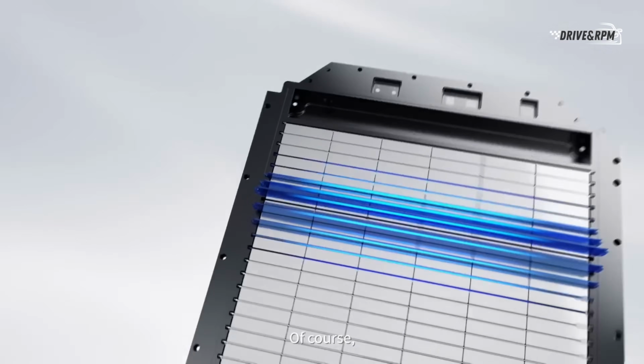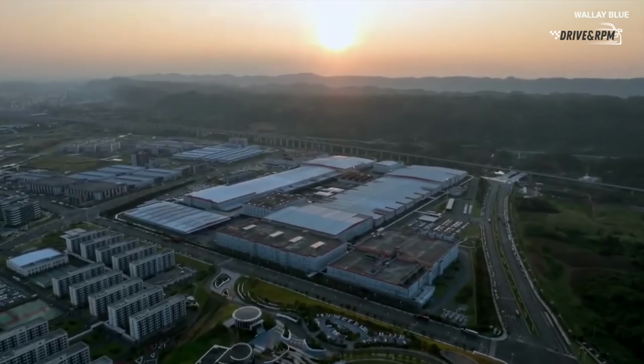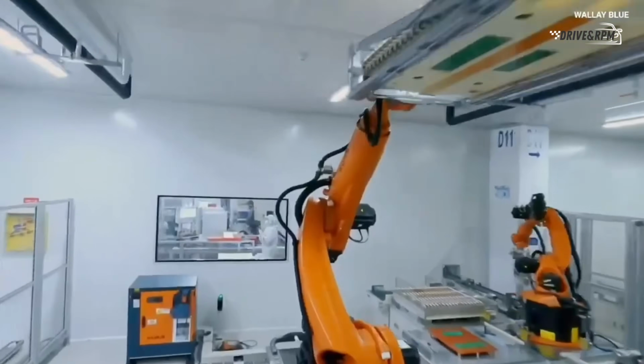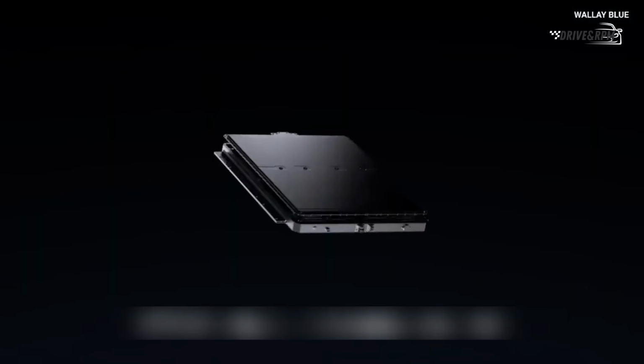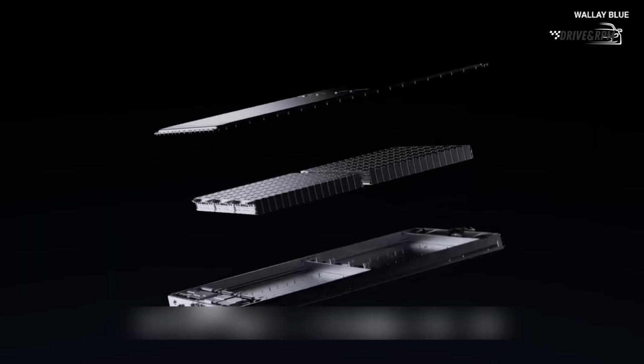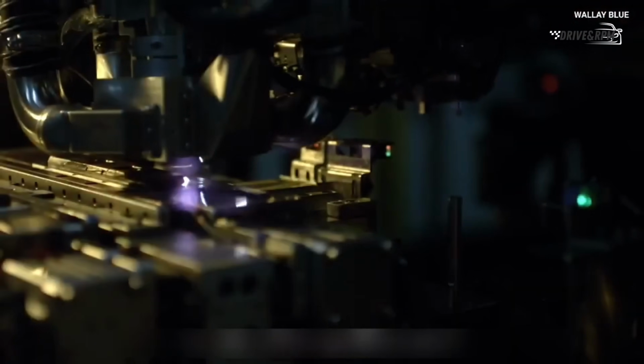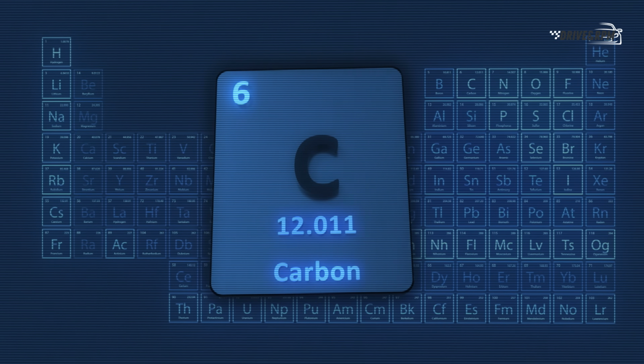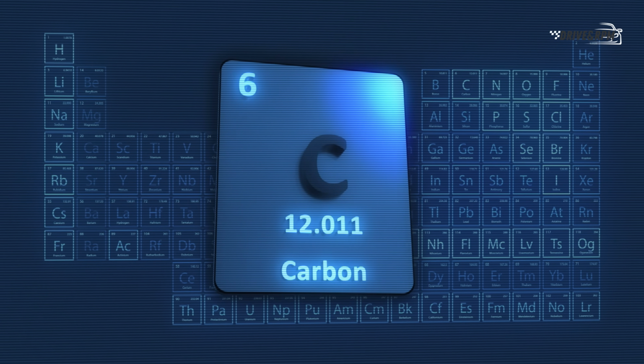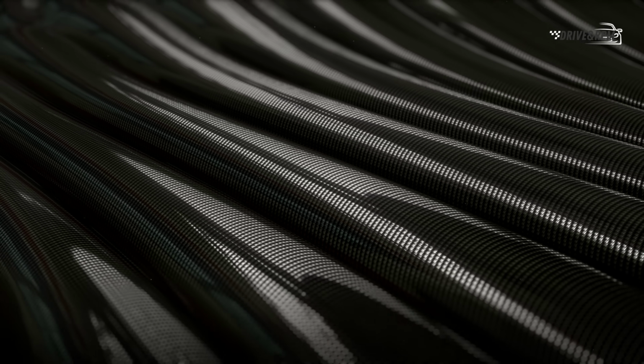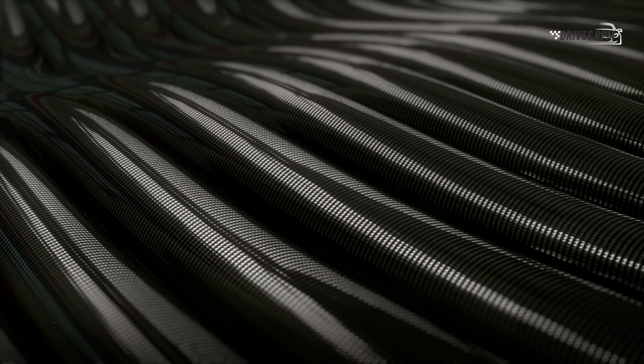But CATL just broke the system. They realized you cannot force sodium to play by lithium's rules. So, they entirely abandoned traditional graphite. Instead, their engineering teams developed a highly complex, proprietary material known as a hard carbon anode. Hard carbon is fundamentally different from graphite. It features a disordered, amorphous structure with massive micropores and significantly wider, irregular interlayer spacing. It acts like a highly engineered, molecular sponge designed specifically to accommodate the massive sodium ions without any structural degradation. By utilizing this porous hard carbon, the sodium ions can rapidly enter and exit the anode without expanding or cracking the electrode. This single breakthrough solved the degradation cycle.